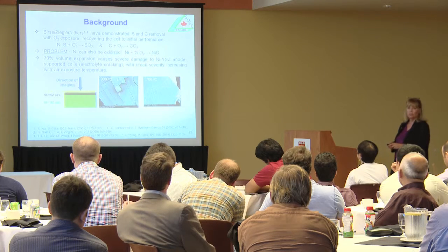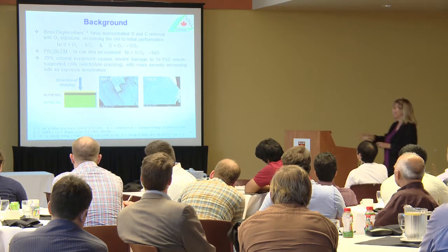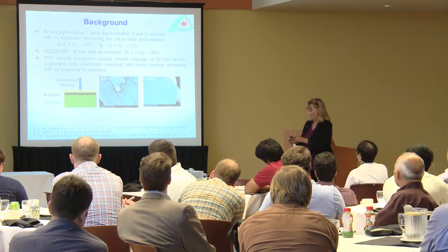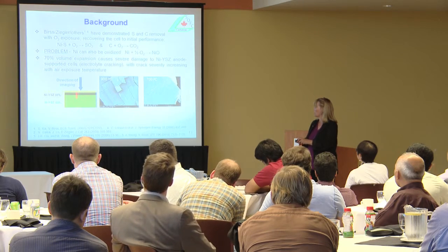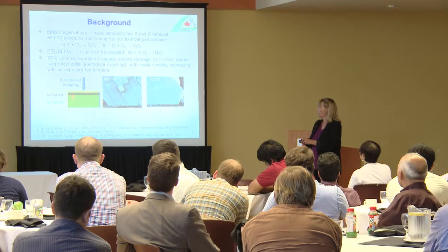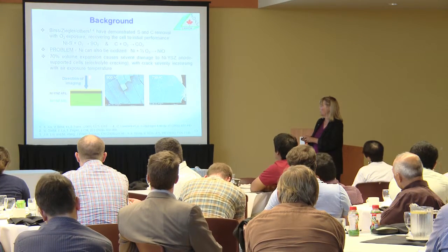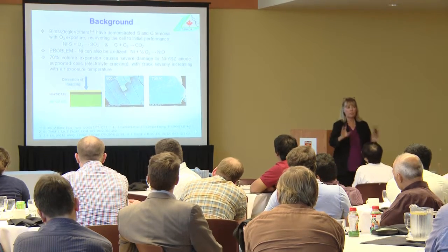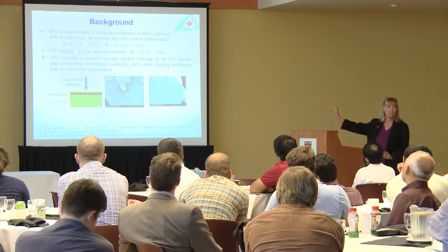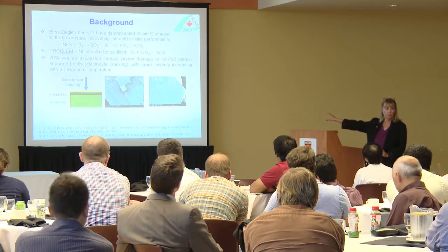And what Jason did in some work is he designed, this isn't a real cell, what you can see is a nickel support layer, the electrochemically active layer, a thin electrolyte, and we're looking at the top down on this. And you can see that if you 100% oxidize the nickel phase at high temperatures versus lower, there's a very big difference here. It's much worse at high temperatures.